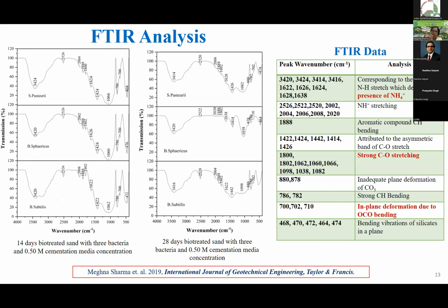And through the FTIR analysis, through the peaks of the bands, we can say the ammonium presence was observed. If the ammonium presence is observed, it means the biogeochemical reactions happened. Okay, and CO stretching and OCO bending confirm that the carbonate precipitation is there. Okay, so all these methods help you to know that the precipitation occurs and that a particular type of mineral occurs along with quartz, the calcite precipitation.